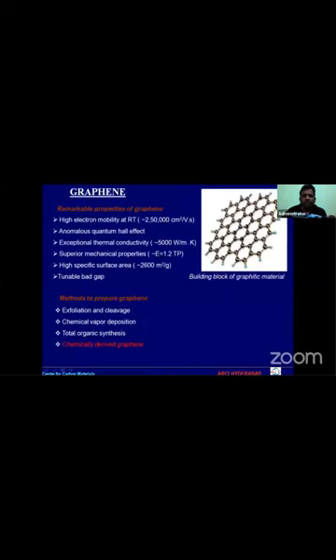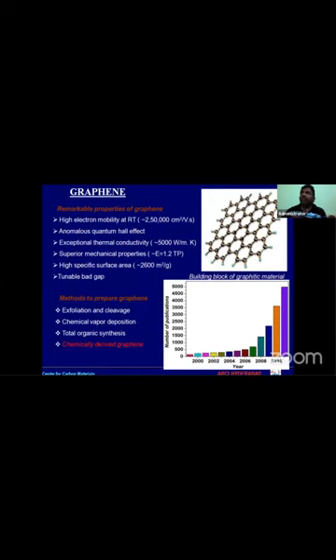Graphene is a very different type of material, which has a combination of very high electron mobility, the anomalous quantum Hall effect, and exceptionally high thermal conductivity, 5,000 watt per meter per Kelvin. The superior mechanical properties, modulus is 1.2 terapascal. The surface area is 2,600 meters square per gram. And a tunable band gap. You cannot imagine any other material which has a combination of these properties.